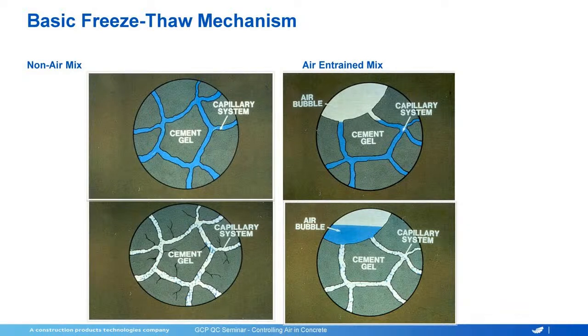So here's what happens. I have a no air mix. I don't have any air voids in here. You have the hardened concrete. I have water get in here. Now down below that, I have these capillaries full of water, and they are freezing. And you can see in this illustration, I'm starting to get some cracking. Usually we see this on the surface of the concrete. We don't necessarily see the cracking. What we see is the top coming off, but the cracking is where that starts because we're exerting this internal pressure on a system that can't handle it.